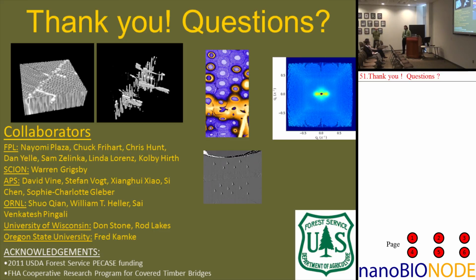Those are a stack of images taken consecutively? Yep. Actually, I set those up to run so I could go home and sleep. But yeah, that started out at like 99% humidity, and then I did a step change to 0, which takes about 1 minute inside the chamber, and then those experiments were collected over a period of about 8 hours. I can show you the movie again, and the times are actually on there to get an idea.